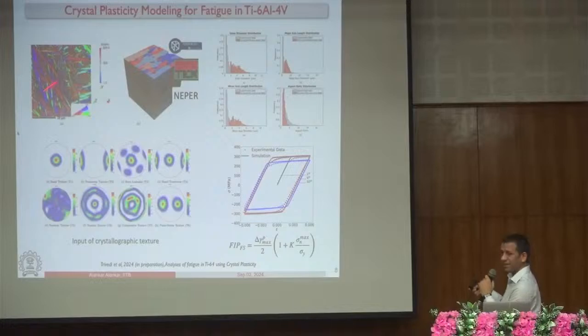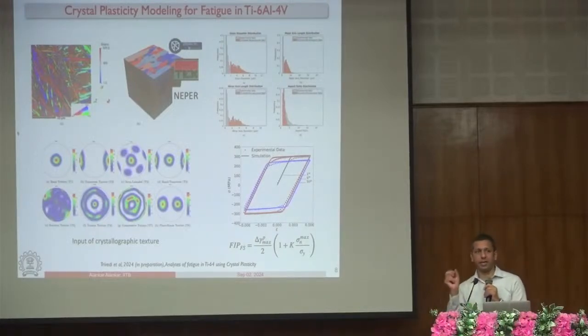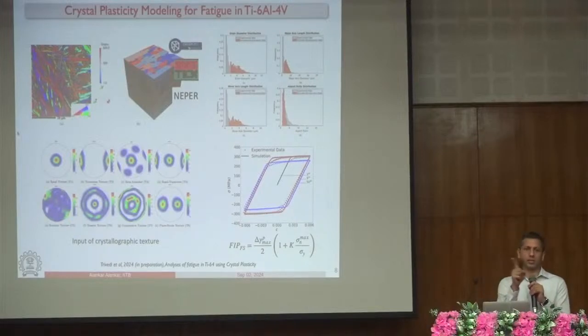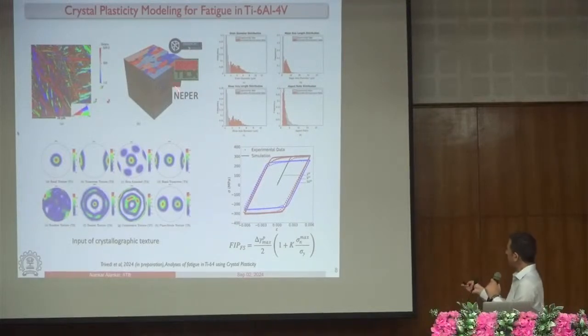And you don't see exactly needles in this because the size of this RVE is much smaller than the size that you are seeing here. But the statistics that you see in experiment is completely captured, right? So we are actually numerically talking about similar structures in both cases. So once this structure is ready, we run it through various boundary conditions that replicate cyclic deformation. And along with just the grain morphology, we also now can play with the orientations of these grains. We can assign various types of textures that you see in deformed Ti64 in industry, right?